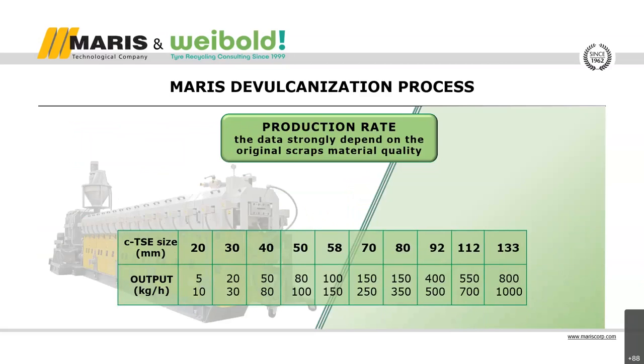Now, the table has the purpose to give you an idea in terms of production rate in our extruders. From a laboratory scale to the big machine, we can cover a big range of production. It is, however, important to underline that those data strongly depend on the original scrap material quality, as I mentioned before. So, for example, for a laboratory scale, that means our 20 or our 30 millimeter, we can produce from 5 kg per hour to 30.